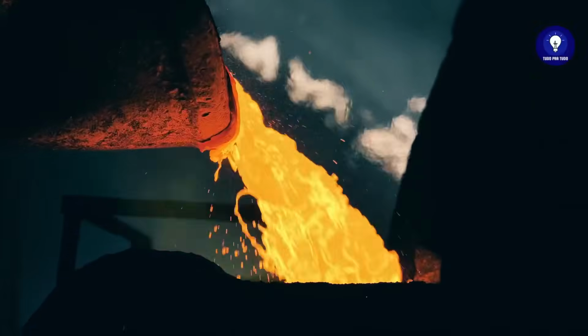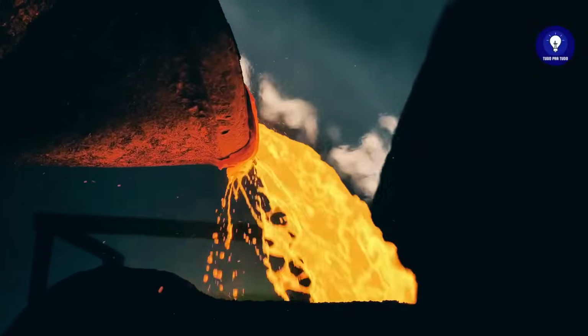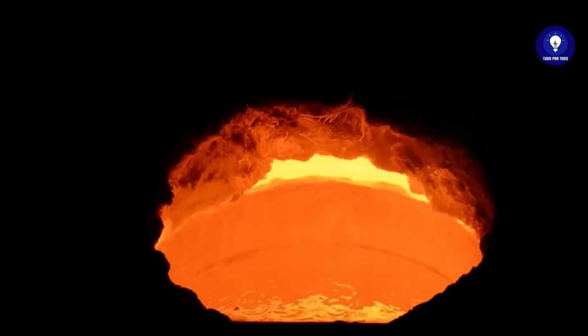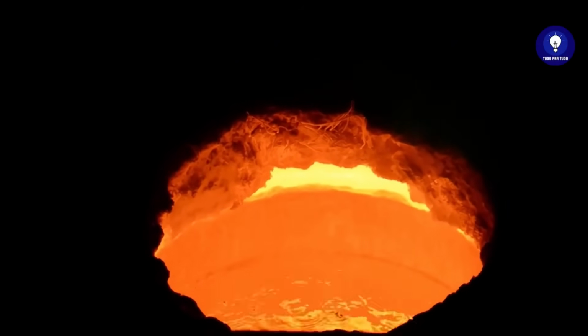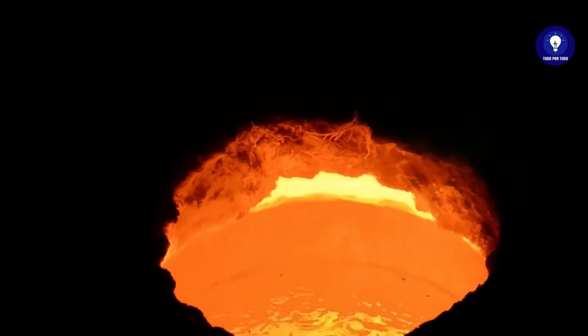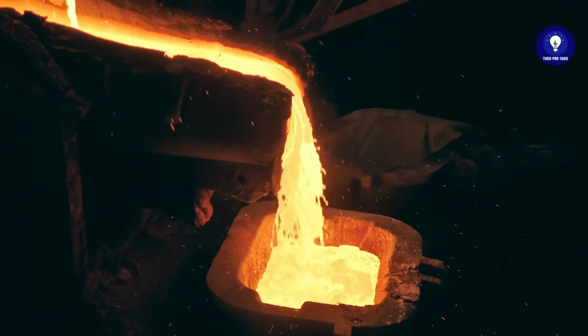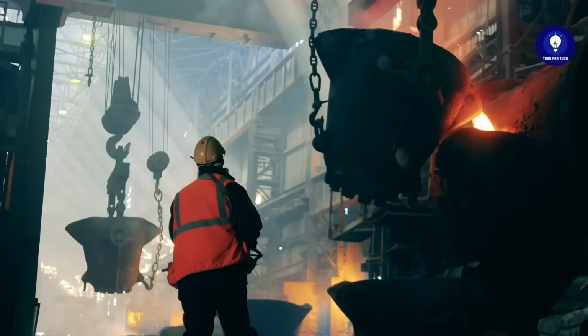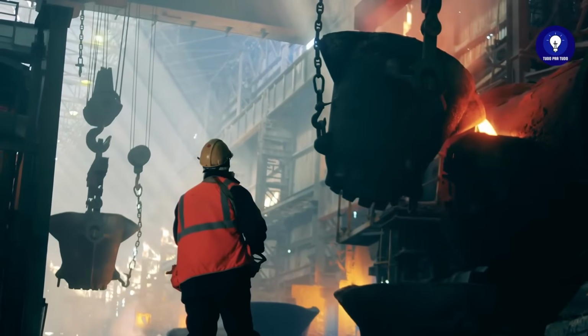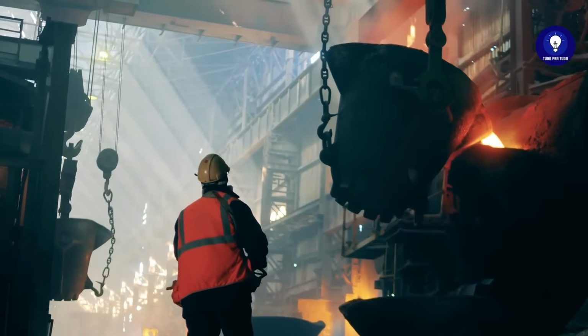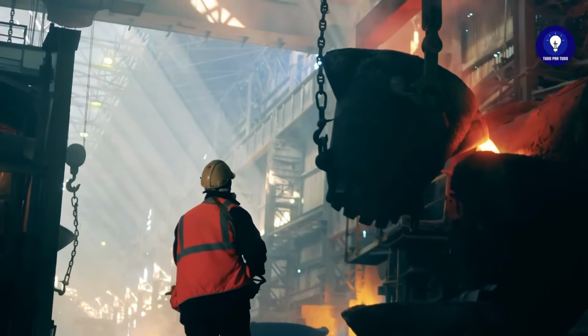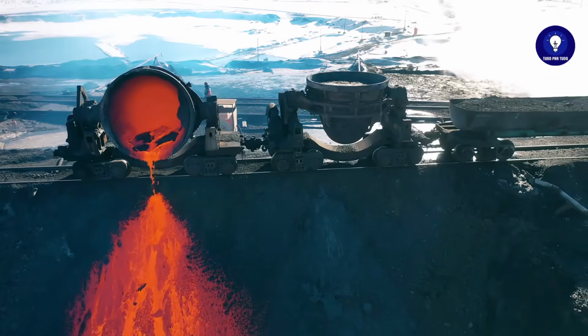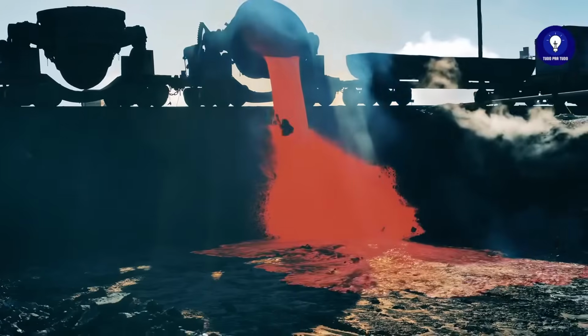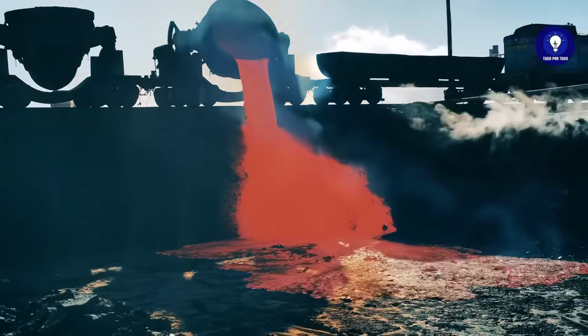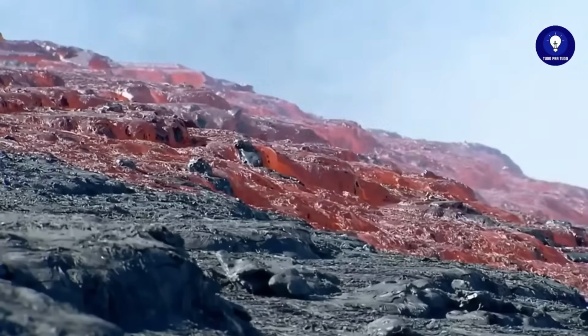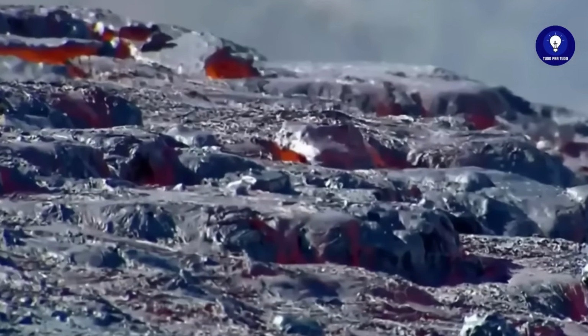At extreme temperatures, the mixture turns into a glowing liquid. The slag, made up of iron and other minerals, floats while the copper sinks. At this point, it already reaches a purity of 60%. Next, it goes into a second furnace, where the copper content rises to 98%. The molten residue is poured onto a pile, a stream of glowing slag that flows like molten lava. As it cools, it solidifies and becomes part of the landscape.